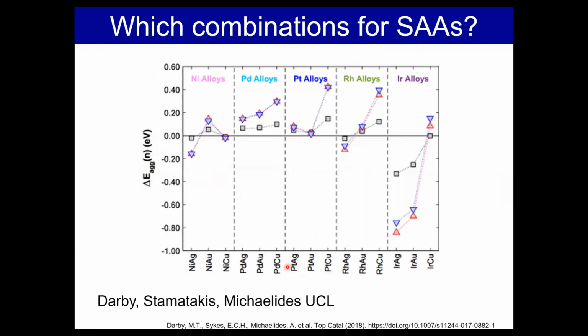Yeah, to reiterate, a lot of these combinations I'm showing here, thermodynamics drives the atomic dispersion, because if your aggregation energy is positive, your tendency is to isolate palladium atoms in the gold surface is more stable than a cluster of palladium atoms. So for a lot of these metal combinations, it's just the mixing thermodynamics that gives you the atomic dispersion, where a lot of these combinations work, but not, for example, iridium silver would be a bad choice. Now, in terms of stability, the thermodynamics keeps it well isolated, but then in terms of a reaction, you're going to have reactants on the surface, and that's what stabilizes the atoms in the surface, whereas if you flow hydrogen or helium, they may disappear into the bulk. So it's really the reaction intermediates on the surface are stabilizing those single atoms in the surface layer and allowing the catalysis to proceed.